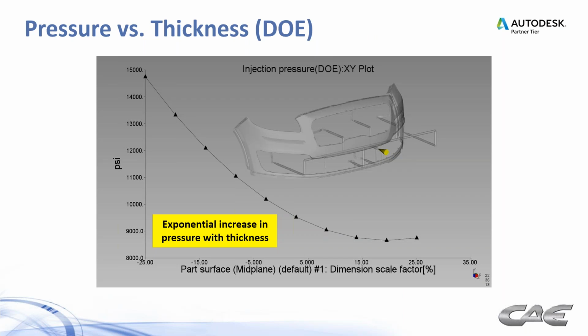Here's a chart. I did a little DOE on this part. Looking at the x-axis here, 5%, 15, 25, and 35% increases in wall thickness from nominal, and then 25% less. So you see from nominal, as you go thinner and thinner, we have an exponential increase in pressure with the thickness. Okay, so it doesn't take long before this pressure starts to get out of hand.